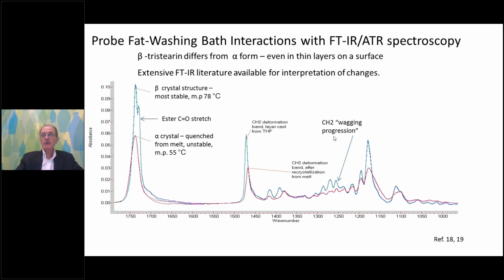So we can establish our layer of tristearin in different forms on the surface of our IRE, right? That's step one. We can cast the beta form, which is the thermodynamically stable tristearin form. We can cast that from solution and obtain the spectrum of it. And we can then obtain the more unstable alpha form by melting that layer and then quench cooling it to obtain the alpha form. And we see indeed that the spectra are different. The ester carbonyl differs between the beta and the alpha form. The CH2 deformation band is significantly shifted and different. And there are a series of CH2 so-called wagging band progressions that distinguish the two crystal forms of the tristearin.